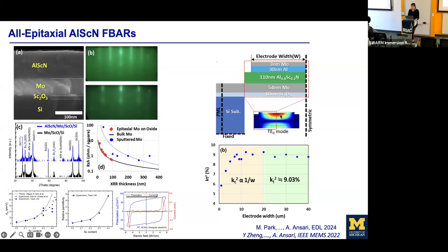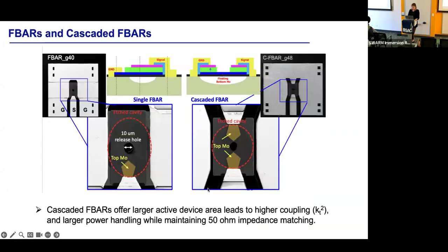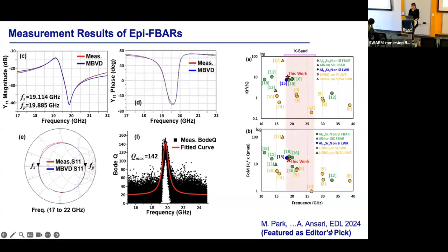Now with this, we optimized the FBAR for having a high kt², and we were able to fabricate two types of FBARs. One is single FBARs, and the other is series connected or cascaded FBARs, where each of the FBARs is matched to 25 ohms instead of 50 ohms, so you can increase the area and therefore get a larger kt². This work was published in Electron Device Letters and was featured as the editor's top pick, where we showed a very nice 18 gigahertz peak, very clean, no spurs around it, with a high kt² of about 10%.